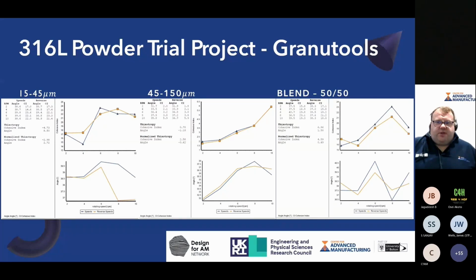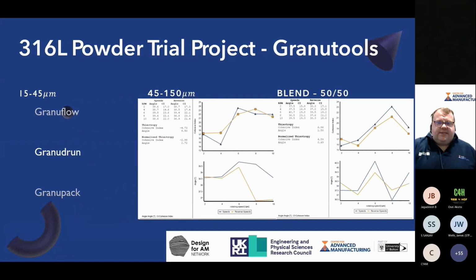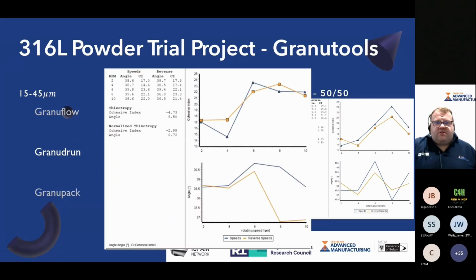And again, perhaps unsurprisingly, we see a nice clean graph on the large powder. Powder dynamics of large powder is expected to be a little bit better, I would say. If we just zoom in, what we see in terms of the 15 to 45 microns is quite an interesting powder, which certainly starts to show some potential shear thinning when the speed starts to increase, and the reality is the next stage of this powder test should be to test at a higher speed, more indicative of what we will see in a recoater kind of acting on a powder.